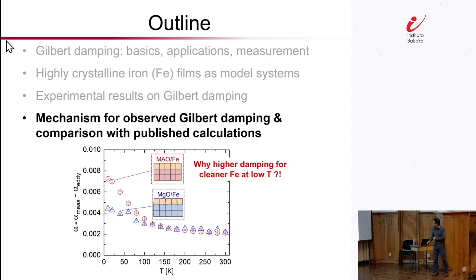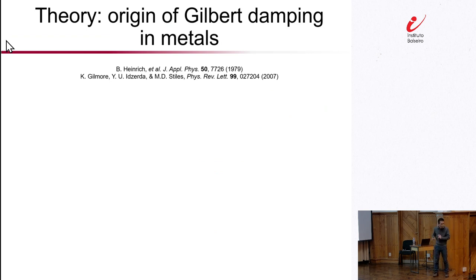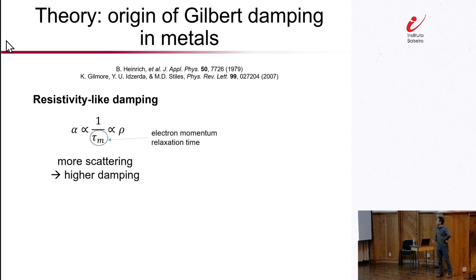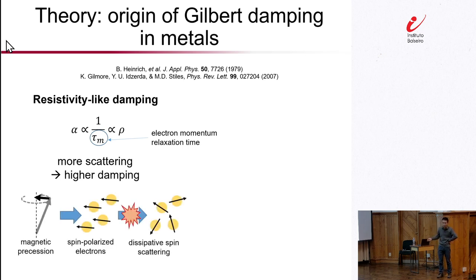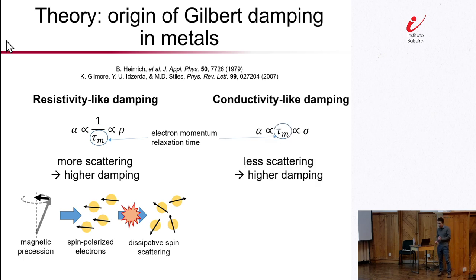Okay, so I'm going to wrap up this talk by giving you a theoretical explanation, which turns out to have existed since the 1970s. So this is a really old study. And these theoretical studies reached a consensus that in magnetic metals, there are two types of intrinsic Gilbert damping. One is what we call resistivity-like damping, which is exactly the type of damping that we would have expected: electron scattering leading to spin scattering, leading to more damping. Okay, so you can probably guess what the other type of damping is called. It's called conductivity-like. That's exactly the type of damping that is quite mysterious, where we get higher damping with less scattering. And of course, where does this come from, if the eddy current damping is not the explanation?